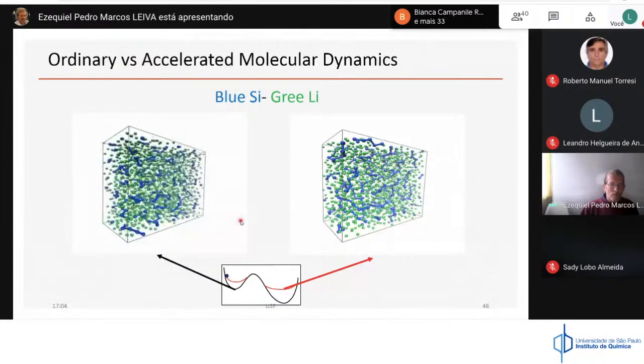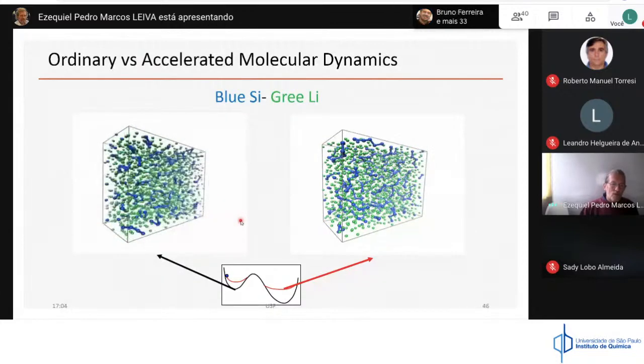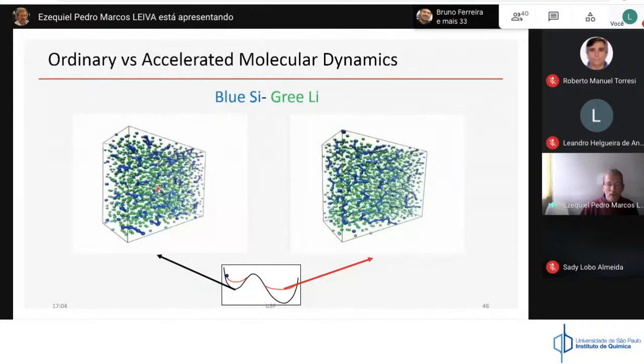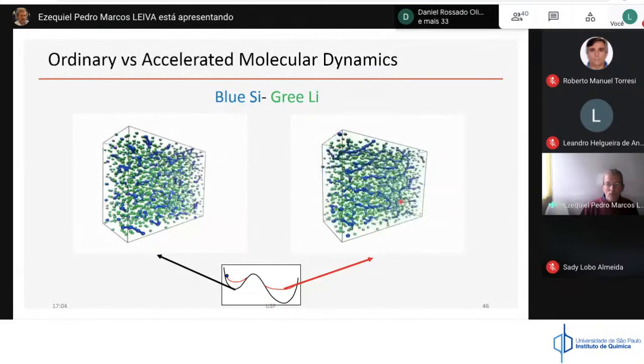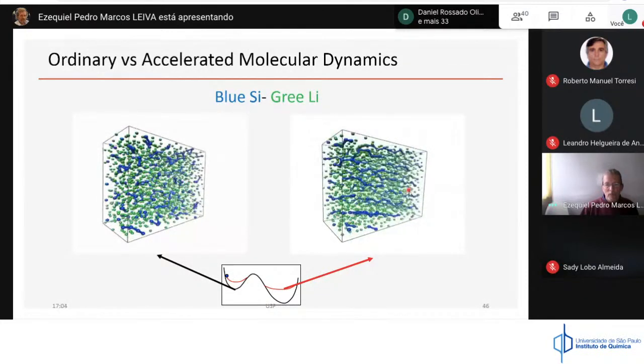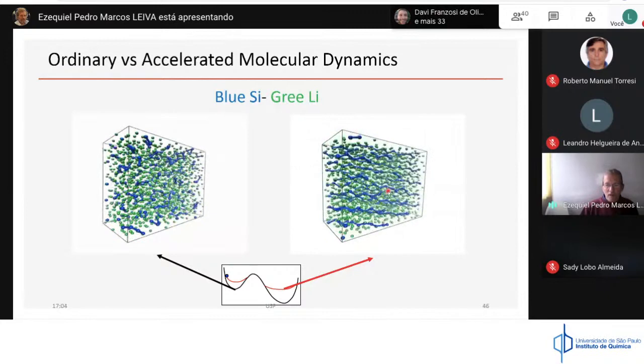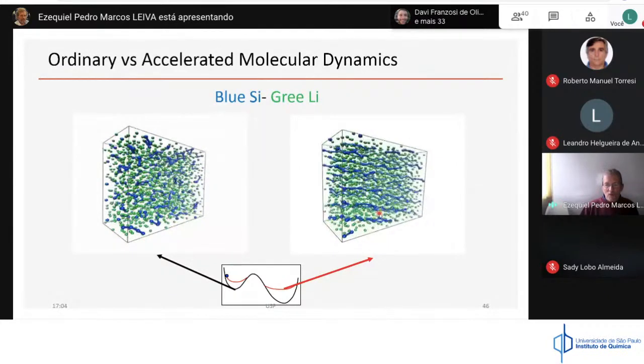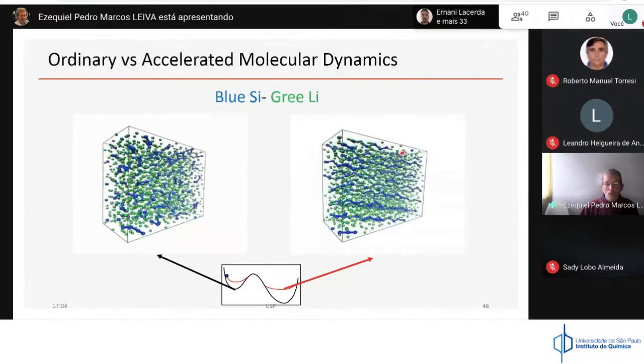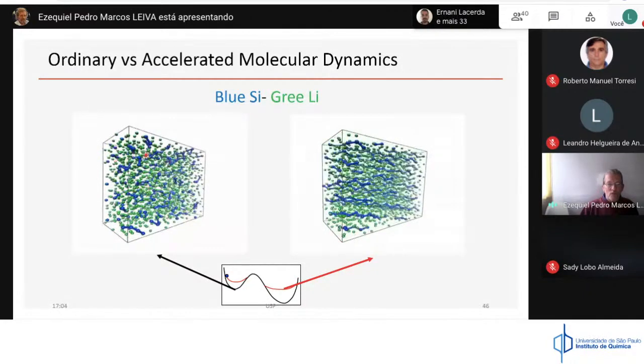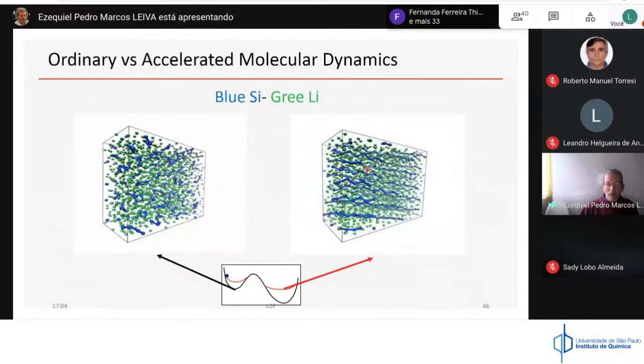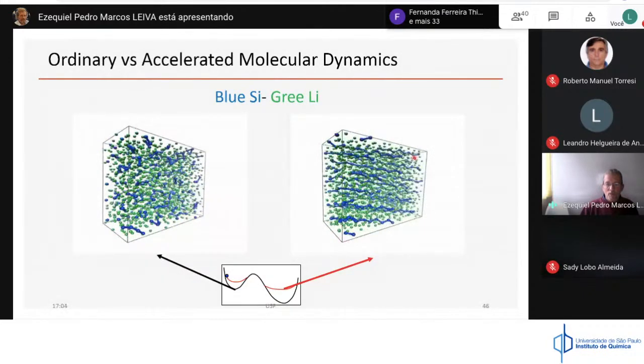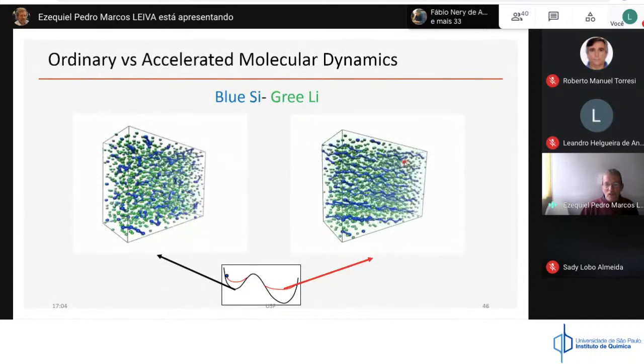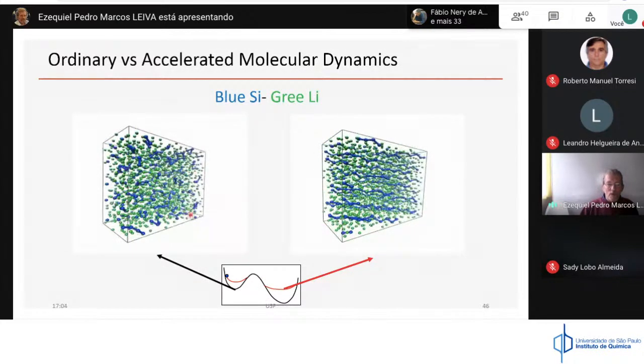You can see some evolution, but when you make an accelerated molecular dynamics, you see a very, very different evolution of the system. On the right, you can see that some chains are formed, and there is no way that you would be able to get that by the simulation on the left. By making this accelerated molecular dynamics, you can get this structure that by no means you would be able to get by ordinary molecular dynamics. This is the procedure we use to get these structures.